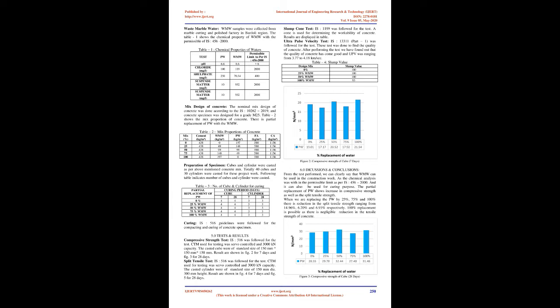456-2000. Mix design of concrete: the nominal mix design of concrete was done according to IS 10262-2019, and the concrete specimen was designed for grade M25. Table 2 shows the mix proportion of concrete. There is partial replacement of PW with the WMW. Preparation of specimen: cubes and cylinders were cast as per the above mentioned concrete mix. In total, 40 cubes and 30 cylinders were cast for this project work. The following table indicates the number of cubes and cylinders cast. Curing: IS 516 guidelines were followed for the compacting and curing of concrete specimens.